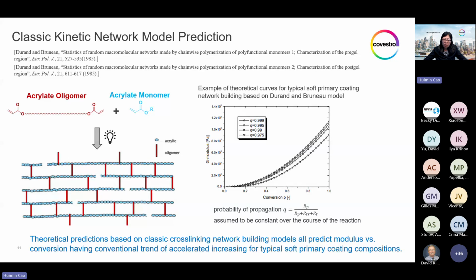And the prediction based on this probability statistics model naturally shows this conventional shape of accelerated increase of modulus versus conversion. And this statistic model did not even use the pseudo kinetic first order assumption, but it still reached the same conclusion, describing this accelerated increasing shape of modulus versus conversion. So then the question becomes, what makes our new generation coating no longer bound by this classic behavior of UV curable coating for optical fiber?